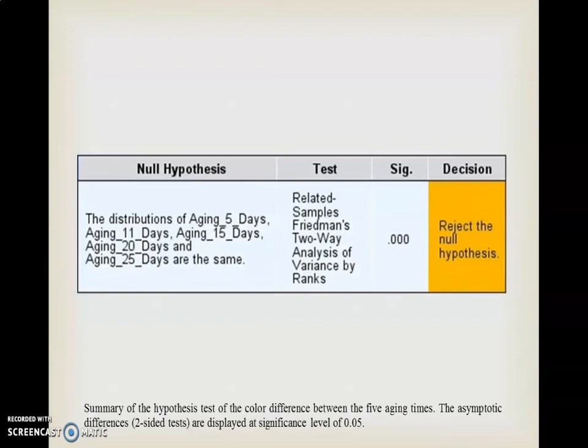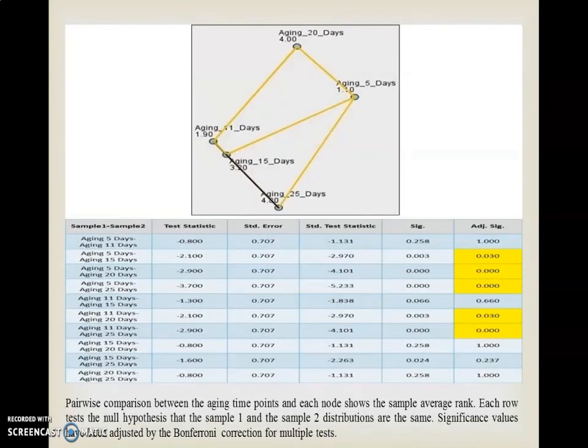Also, to ensure whether the significant difference in the color difference is by chance or there is an actual difference, we used a statistical method. The data didn't assume the normal distribution curve, so it didn't meet the repeated measures ANOVA. There was another method, Friedman ANOVA. It showed the rejection of the null hypothesis. There is a significant difference. We used another step, post hoc methods, using the Bonferroni correction to locate which pairs are different, at the ages 5 and 11 days with different days.